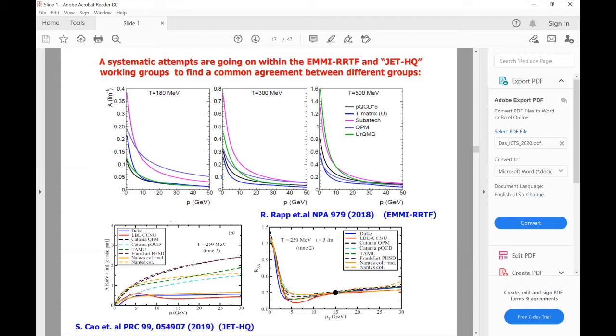This is because some people use only collisional, some people use collisional plus radiative, some people use a constant coupling, some people use running couplings, and the scale is also different. Sometimes it runs with the temperature, sometimes with the momentum, and in some cases people use Langevin dynamics, in some cases Boltzmann dynamics, sometimes the cross sections are forward peaked, sometimes isotropic, and so on. So work is going on to understand this much better and how different groups can really converge and extract the heavy quark transport coefficient.